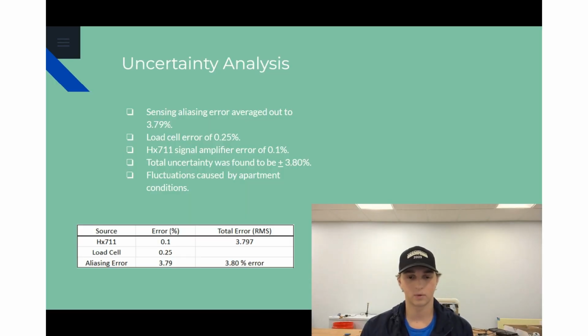Our main source of error came from the sensor aliasing. This error derives from differing frequency in the load cell reading and the switch activation. In simpler terms, the load cell amplifier is collecting data at 10 Hz, which is at a different frequency than the peak activation force, which is what we were looking to record. This frequency offset creates a cyclical variation in the data, which can be approximated by taking the average half height of the cyclical variation from each test. This error averaged out to 3.79%.